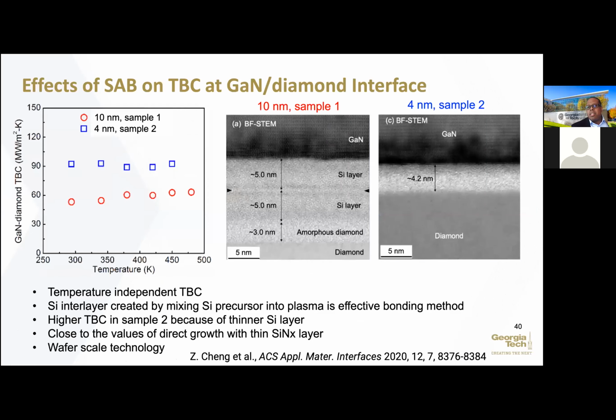And so this is what you see. If I deposit the silicon layers here, you basically get some amorphous layers that are actually occurring. You typically see this amorphous carbon here. You get some more amorphous areas, and you get the silicon layers. If I do the in situ, you will also see, I don't have the TEM showing you, there's still some amorphous layer here. You get a very thin layer of a silicon containing material. But what you do see is that for this sample here with the thick inner layer, you're down here around 60 megawatts per meter squared K.